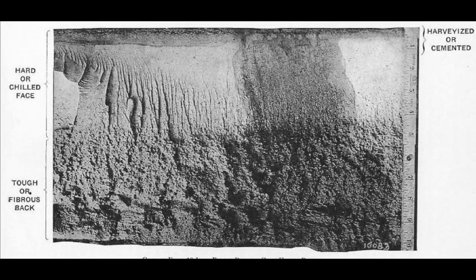and why it is superior to regular steel, because you have all the resistive benefits of a really hard face, in mechanical engineering terms, and if that is breached or the armour is hit by a lot of force, then the tough back holds it together and also prevents the overall spread of shockwaves, so it adds an additional toughness and an additional ability to resist incoming shells. So it affects the material properties of the steel quite immensely.